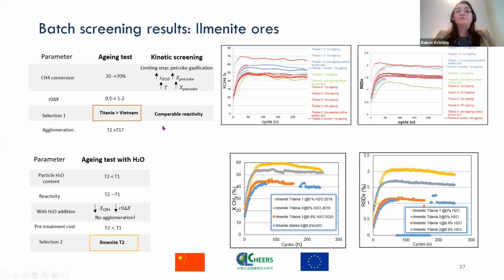However, we still had to make the choice between the ilmenite T1 or T2 material. They are quite similar. They come from the same mine, so composition is almost the same. However, ilmenite T1 has higher water contents, which leads to the fact that ilmenite T1 shows higher agglomeration affinities. And this could be problematic in the condition of continuous circulation.